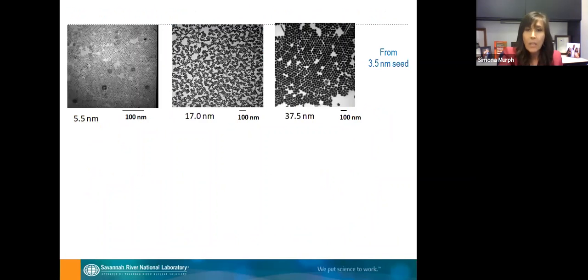And if you take a look, you see a wide array of different size nanoparticles. Once you get to around 40 nanometers in size, you can see that some other different shapes appear. And you can see here a couple of rods at the top of the SEM image, the TEM image on the right.